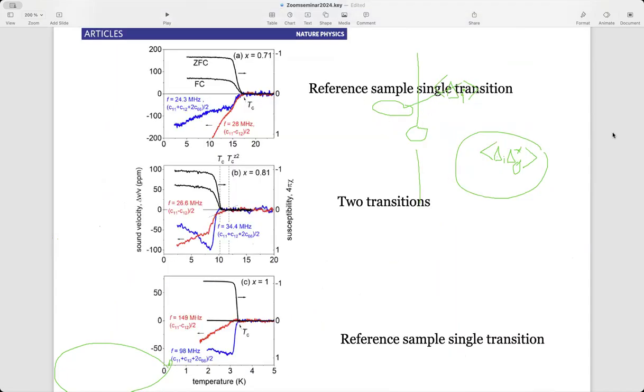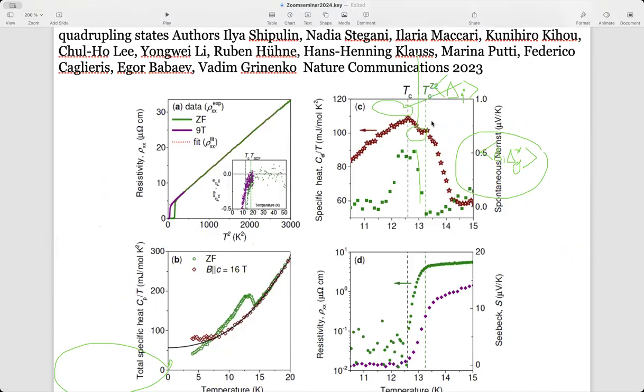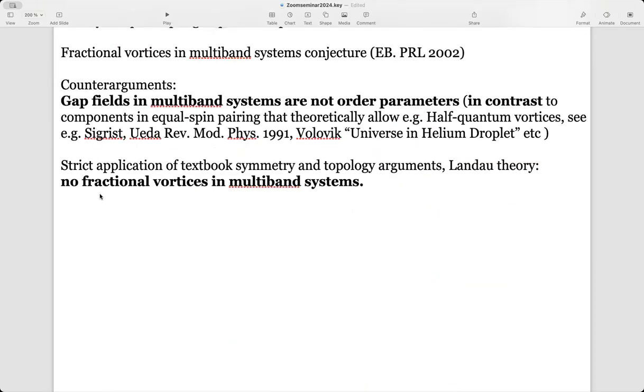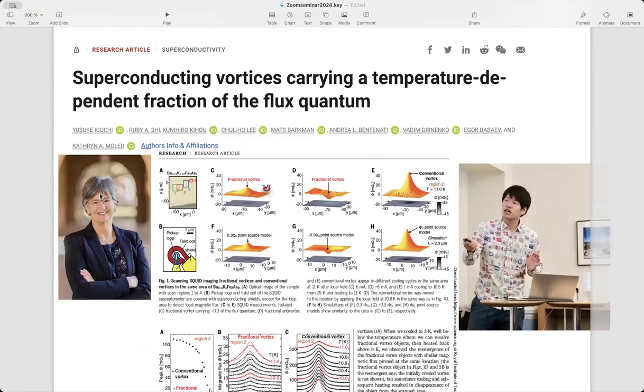Okay, this is another type of ultrasound measurement. This is an example of another sample. There are actually two specific heat features. At the first specific heat feature, time reversal symmetry is broken, but there is absolutely no diamagnetism and no superconductivity, and that develops only at lower temperatures. Most of these critical temperatures are also suppressed by external magnetic field. And what I started with at the beginning, all the arguments relied on the fact that the magnetic flux quantum should be fractionalized.